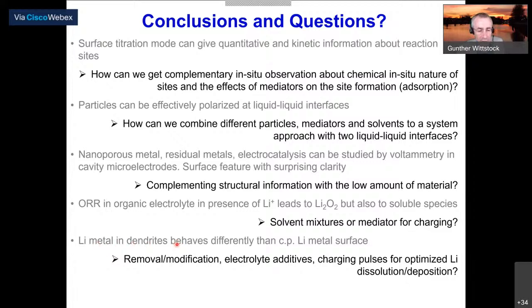And lithium metal forms dendrites, and they behave very differently than commercially pure lithium metal surfaces. So again, removal and modification of these surface layers, electrolyte additives, and charging pulses for optimizing the behavior of lithium dissolution and deposition are, of course, means to do. And it is also interesting to look at that with an SECM and to handle the challenge of deciphering reactivity changes, form changes, and topography. This is what I wanted to bring to you.